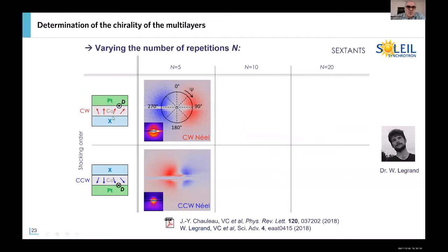We apply this technique to multi-layers, platinum, cobalt, I think alumina in this case, for 5 repetitions. And you see what we get on the CCD camera after making the difference between the two polarizations. First, we get the maximum of the contrast on this axis and not on this one. And this directly means that we do have Néel domain walls and not Bloch domain walls.